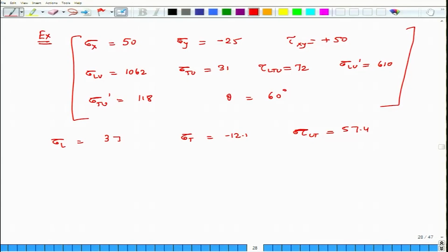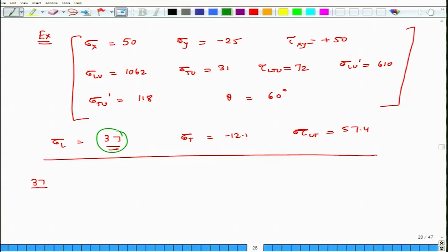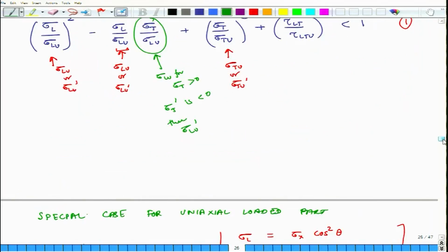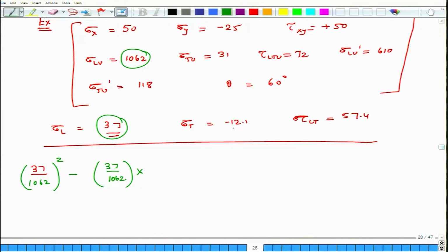Okay. Now, with this condition, let us apply the Tsai-Hill criteria. So, here we have 37 divided by Lu 1062, the whole thing squared, minus 37 divided by 1062 times the second thing. So, what is the second term? Sigma T divided by sigma Lu. Now, here sigma T is minus 12.1, and of course we just take the number, and we divide it by, because this is compressive, so we consider 610.